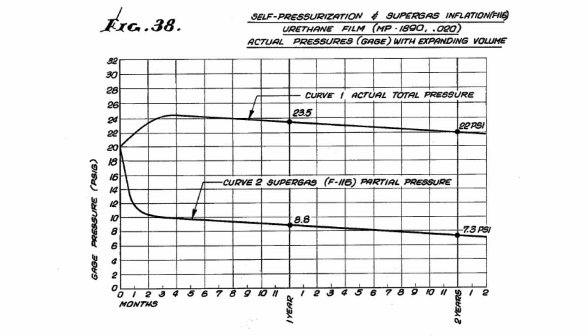The second comment concerns the application of external loads to the inflated insole. When load is applied, the internal pressure of both air and supergas rises. Air pressure rises above the outside air pressure, and therefore some of the air will be forced to slowly diffuse out. Essentially, no supergas will diffuse out unless heavy loads are applied for extremely long periods of time. When the load is removed, the device will reinflate itself back up to the original working pressure through the mechanism of self-inflation. This self-inflation feature works effectively for a device like an inflated insole.